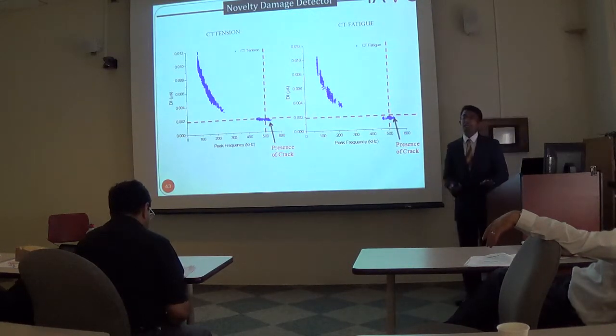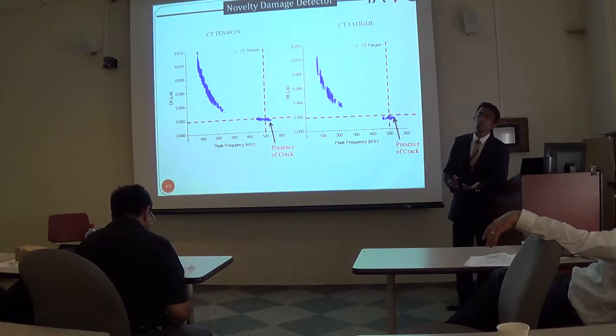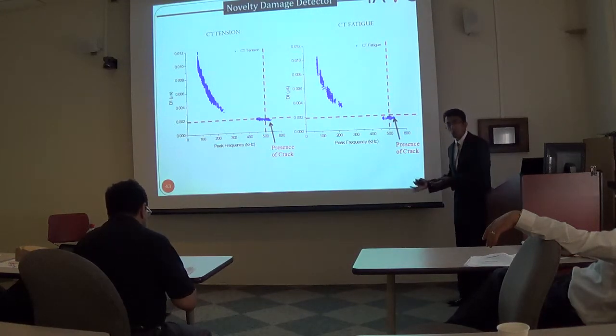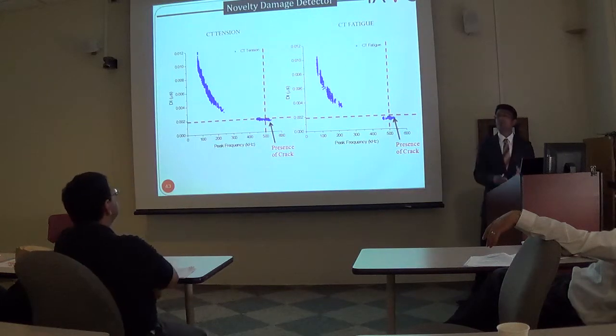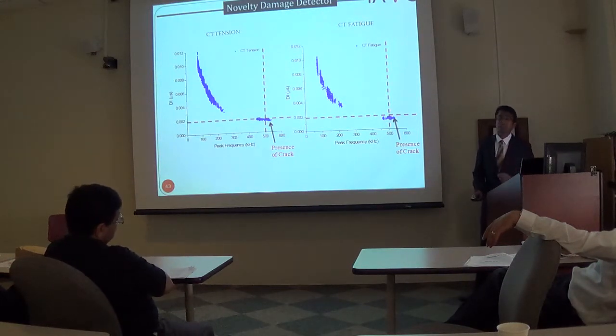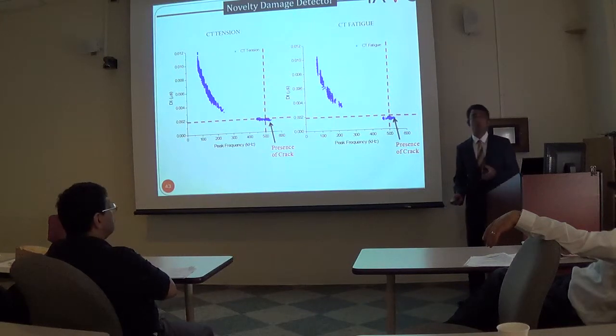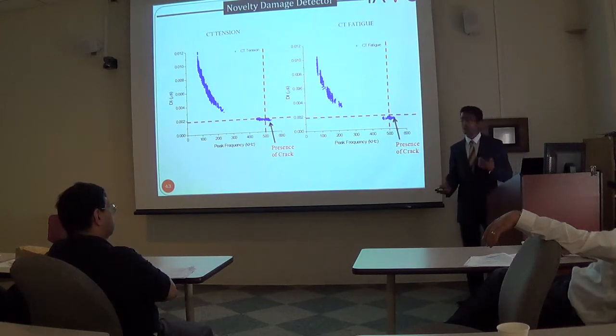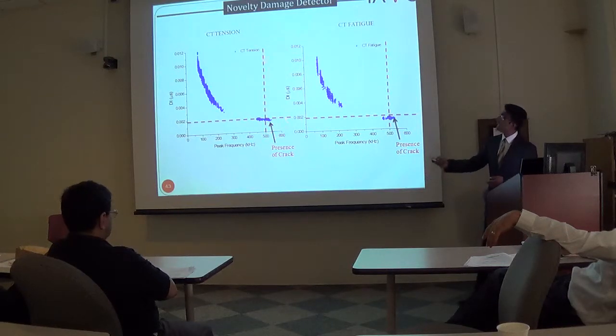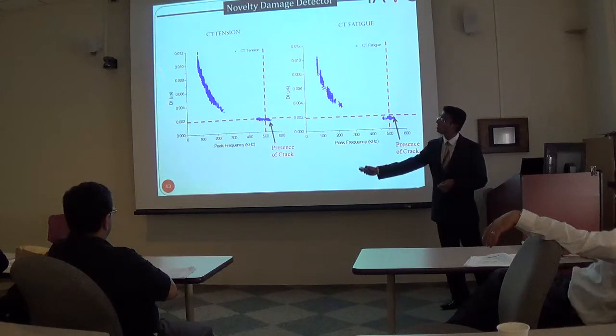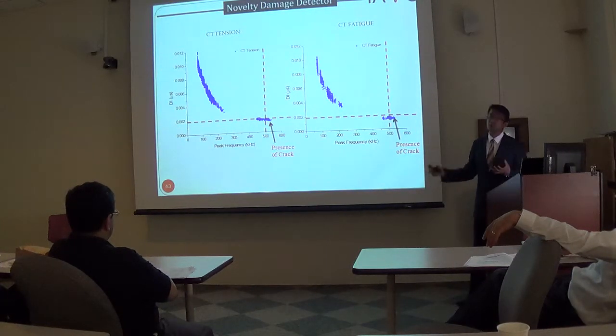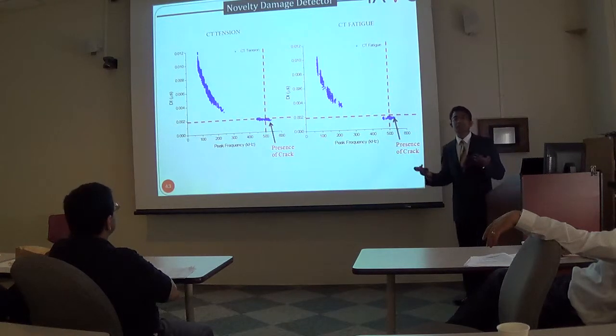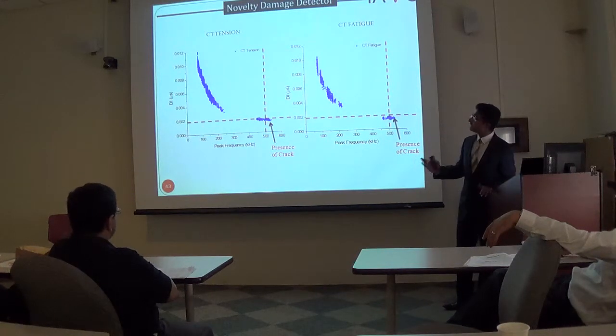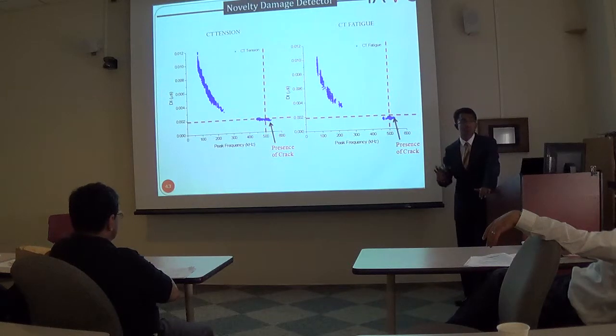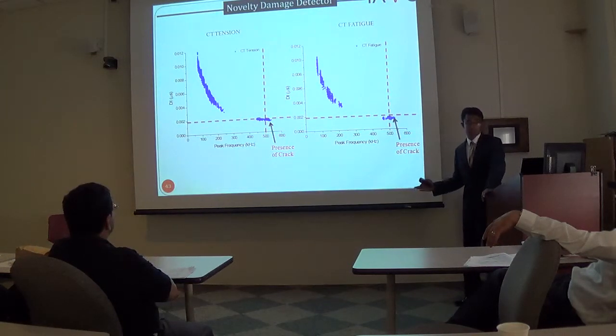So consequently, in order to develop this robust approach, irrespective of the geometry and irrespective of the loading conditions, to hopefully take it from a lab scale to field applications for crack detection, novel AE feature descriptors were designed based on the ratios of the partial power analysis and also the ratio with other features. It can be clearly seen that the signals that were associated with the cracking were seen to fall exactly in the specific region of the damage parameter. So this actually forms the first basis of developing reliable damage parameters using acoustic emission. And currently in the literature, we don't have any damage indexes that utilize acoustic emission signals per se.